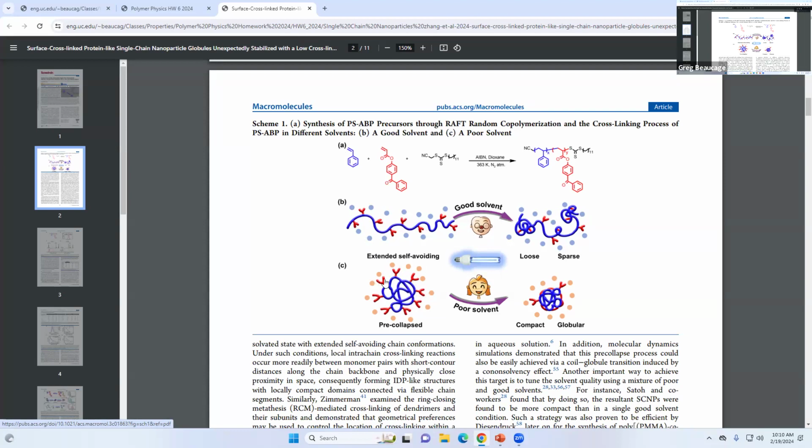And then when he cross-links them, this one and that one will cross-link because the things collapse down. In other words, things that are a large contour length apart will bond together. So then I think on the step of how large the things are, afterwards he's going to put these into a good solvent and then measure the size. And then the size of this thing is going to be larger than that because this thing's glued together into a small ball.